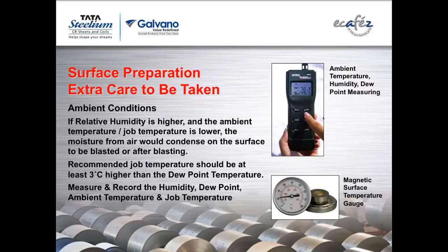And the picture on the right bottom is a magnetic surface temperature gauge. You just put it on the surface of your job, before blasting, after blasting, or both, and check the temperature. It should be higher by at least 3 degrees, minimum 3 degrees, than the dew point temperature. Then you are safe that condensation is not going to happen on your jobs.